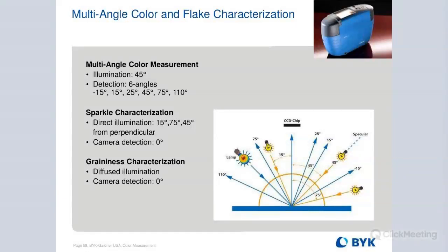And then we measure those in and we calculate absorption and scatter values for all the different wavelengths. And then the software uses all that information to measure an unknown and then come up with the formula. There are different ways to do that. And in our software, you have to tell the software whether you're formulating a solid color, a color with metallic flake or mica. And if you are also trying to formulate a tricoat, where your clear is tinted or has pigment in the clear coat, you have to tell the system that you're going to work with that kind of color, because there's different mathematics going on in the background for the different layers that the instrument measures when you measure color.